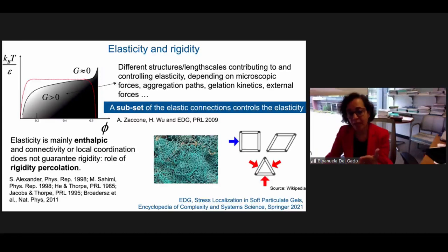The other point that I want to make is that in this system, because I need interaction strength that is sufficiently high in order to start building these aggregates that are sufficiently stable to then grow into these larger scale structures and form the gel, thermal fluctuations are there, but they play, in most cases, a minor role in the development of the elasticity of the system. The elasticity is mainly enthalpic in nature, and one of the implications of this is that just pure connectivity is not enough to provide rigidity.